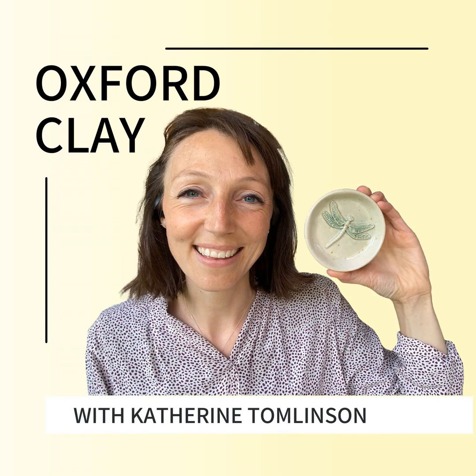But it's really important to sieve a glaze because you do get lumps, especially with Cornish stone. You do get these little lumps, and they basically show up on your pot. So it's a really good idea to sieve a glaze. I think this is like 120 mesh size that I'm pushing it through now.